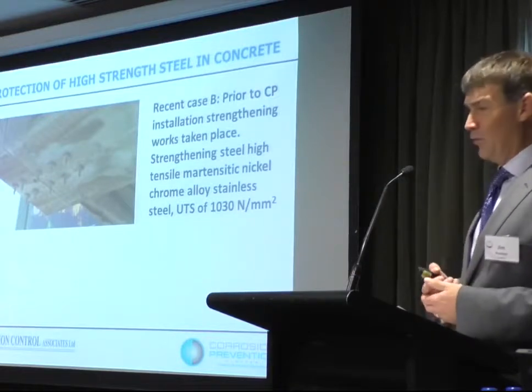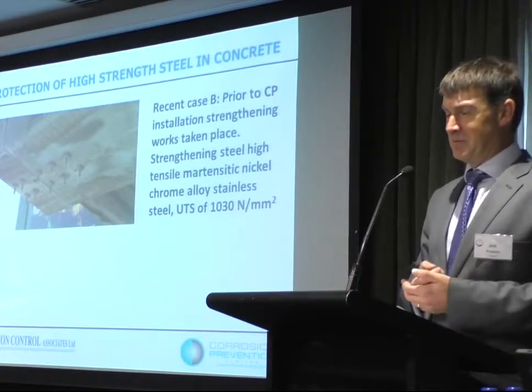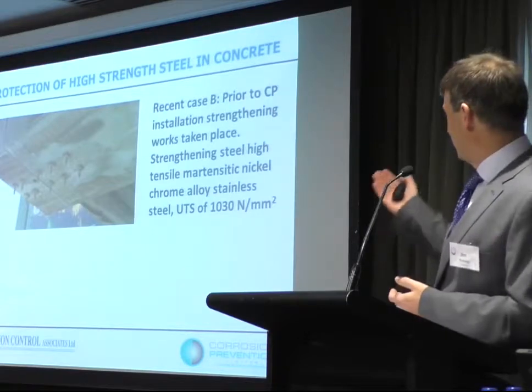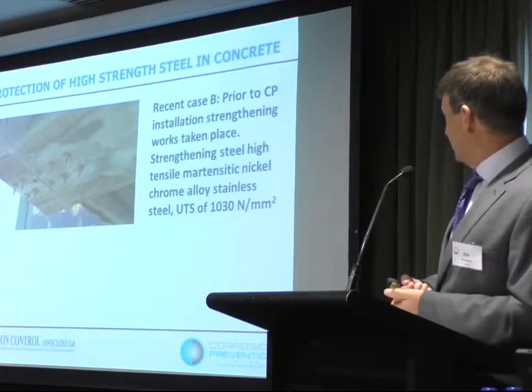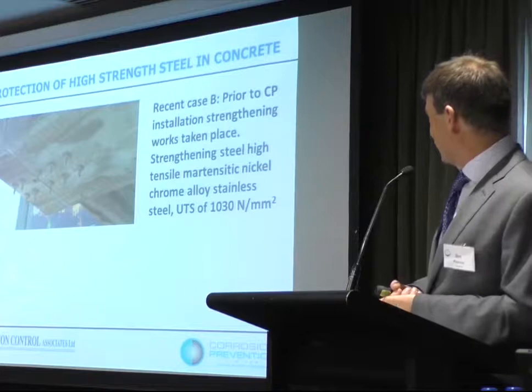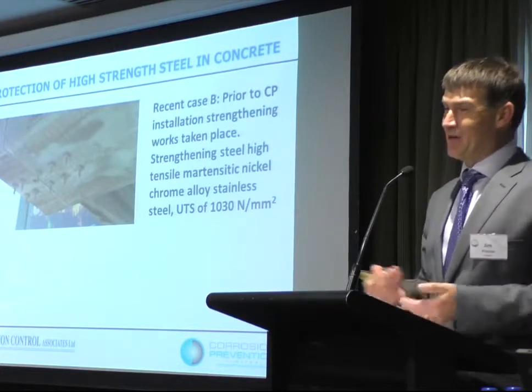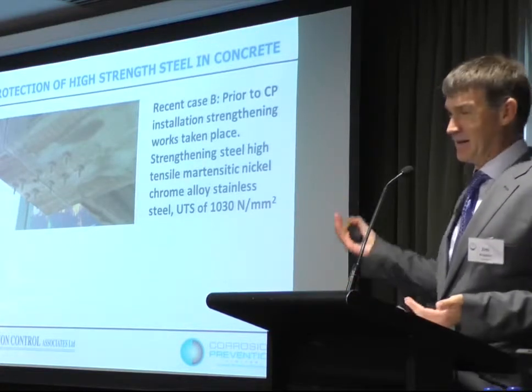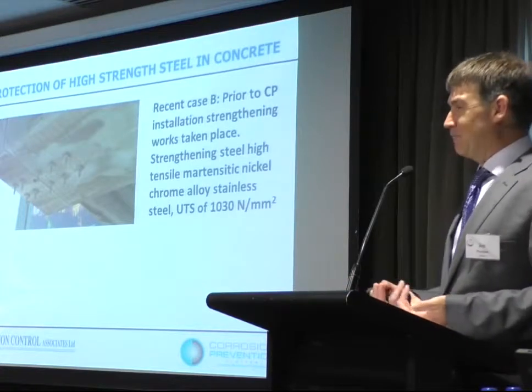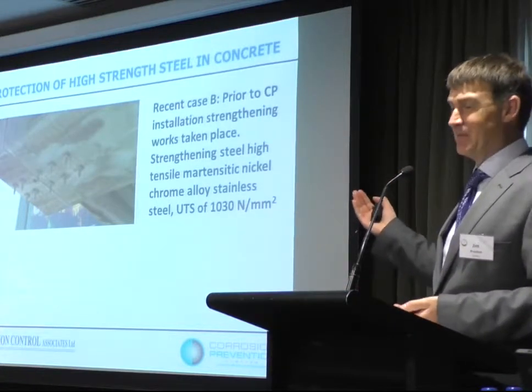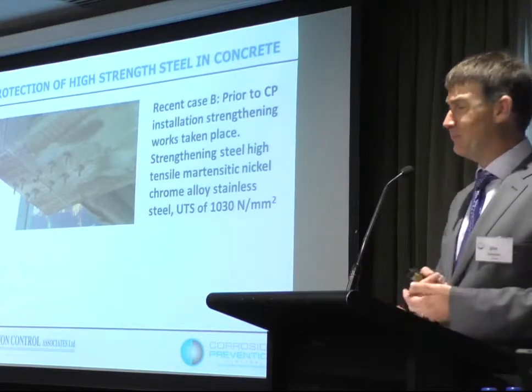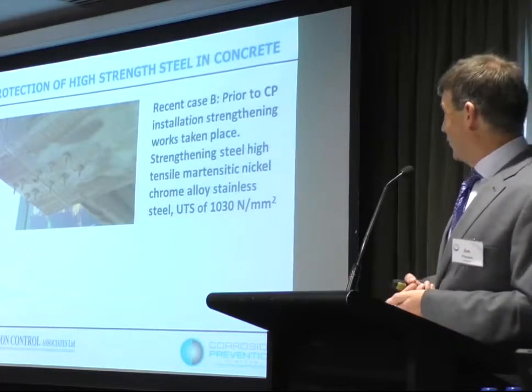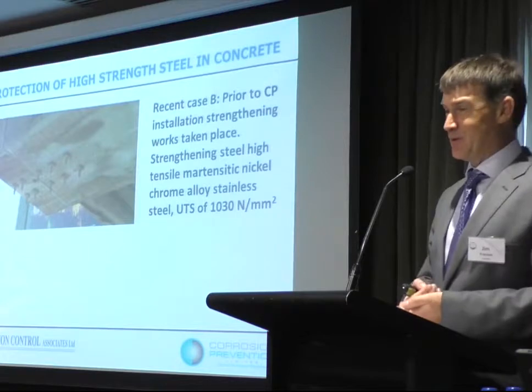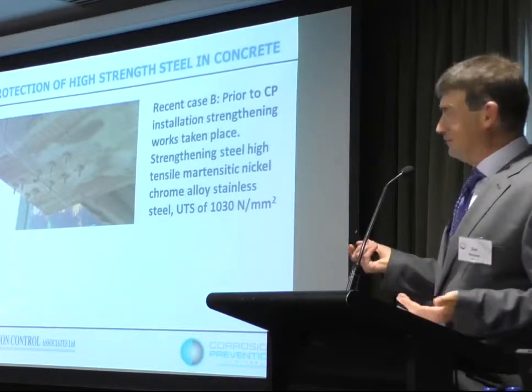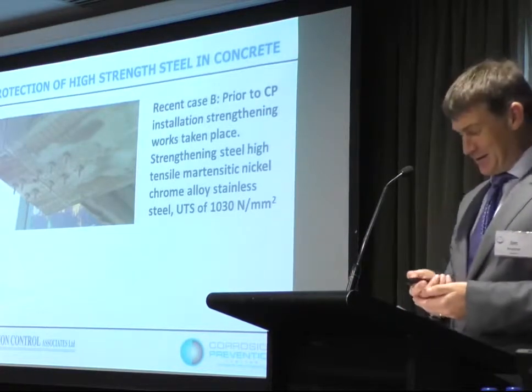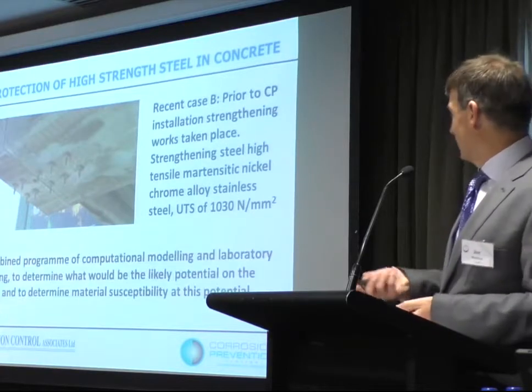Here's another example. Before they called the corrosion guys, the structural engineers put in these high tensile martensitic nickel-chrome alloy stainless steel bars. I don't know why they used stainless steel. I think it's just so the bit that sticks out of the concrete doesn't corrode. But this is more susceptible to HIC than a conventional steel would have been. Subsequently, they wanted to do concrete repairs and install cathodic protection to the structure. Could we do it? Is it at risk of HIC?